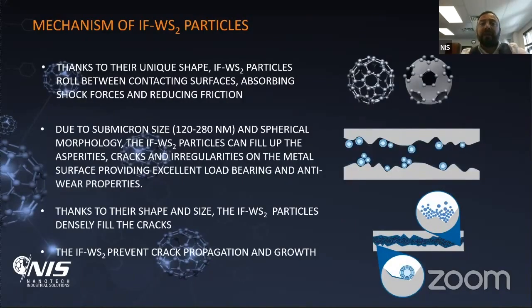So talking again about the mechanism, there are several of those. As I mentioned, yes, there's the effect of ball bearing, the rotation of the particles on a surface. However, the rotation on the surface of the spherical particle is a function of the surface roughness. So it's not going to rotate on any surface. So we believe, also there are probably hundreds of papers showing that IF-WS2 particles do rotate. We believe there's not a predominant effect of the friction reduction of the IF-WS2. The predominant effect is exfoliation of the layers, sliding effect.